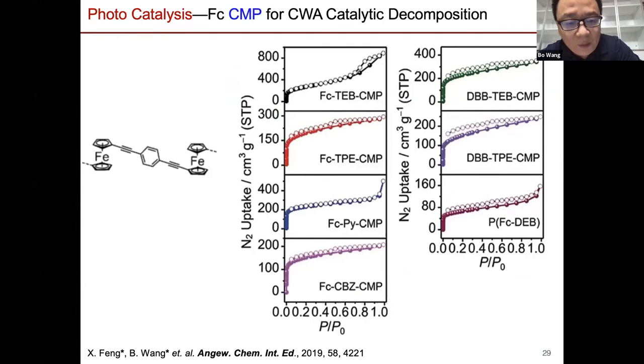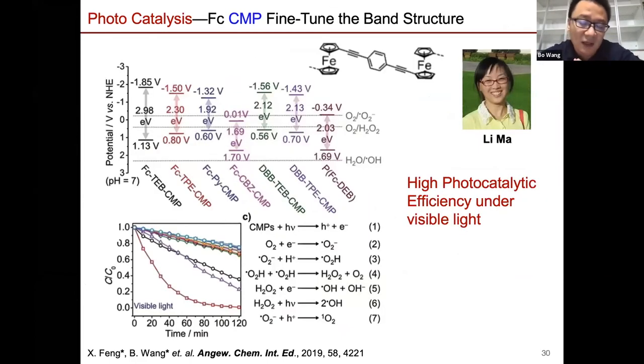And lastly, we use this ferrocene structure. Since it's porous and you have ferrocene in it, can we actually do something with it? We analyzed the band structure of the different ferrocene frameworks. We realized that under visible light, you can generate different types of active oxygen species, either superoxide radical or hydroxyl radical, or in different cases, hydrogen peroxide. So you can always generate different types of active oxygen species. Can we utilize it to decompose, in this case, dye molecules? We tested. It can actually decompose, oxidize some dye molecules.